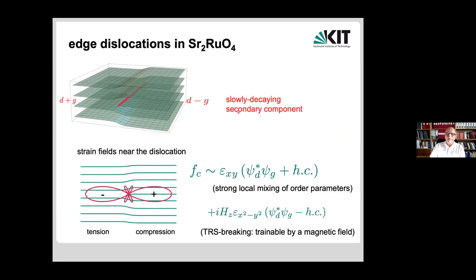So, okay, let's go here. D plus G or D plus iS would do the same job. Both would behave very much the same. And you could even be ambitious and say the difference to identify which one is the right one is to do an STM measurement and see whether you open a gap or not, because one would have nodes and one not in this time reversal symmetry breaking region. If you have D plus iD, it would still potentially work, but you couldn't train it anymore with a magnetic field, because there's no symmetry combination I can come up with where the given strain couples to a magnetic field. And I assume that Aaron would never have seen that behavior in his experiment initially if it wasn't trainable.